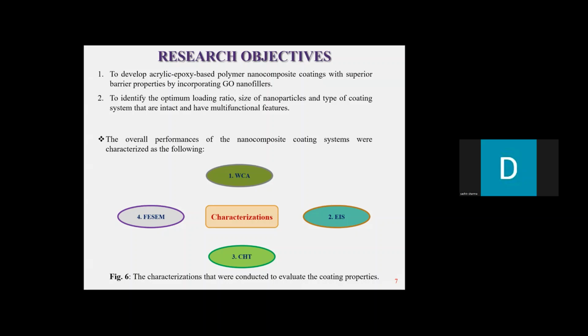So I'll also explain why multifunctional coatings are much better than traditional or conventional coatings. The overall performance of the fabricated nanocomposite coating systems was characterized using 4 methods: number 1, water contact angle, WCA; number 2, electrochemical impedance spectroscopy; number 3, cross-hatch test according to ASTM D3359 standards; and number 4, field emission scanning electron microscope to identify the surface morphology of the coatings.